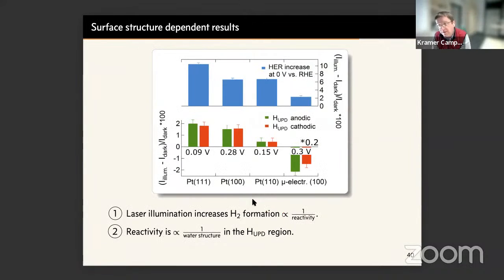Okay, so this seemed a nice framework, and then we said, well, what happens if we now try to look at better defined surfaces? So we did the same experiment. Gregor did the same experiment, now for platinum single crystal working electrodes, and the results are shown here. So the blue is now this laser-induced hydrogen evolution current collected at 0 volts.